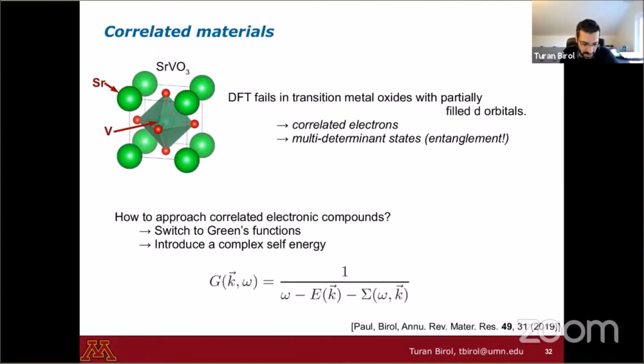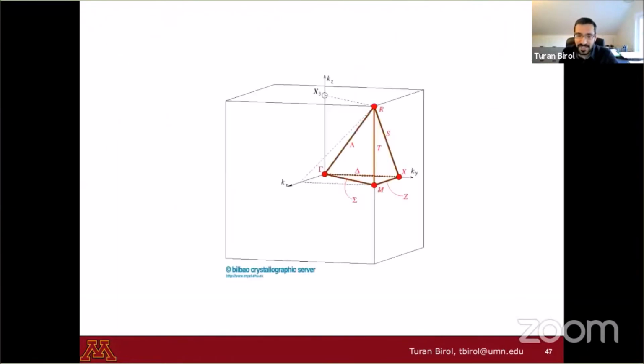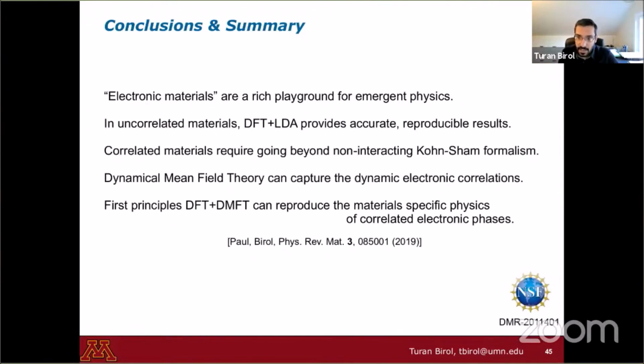That's a great question. So we spent more than a year, and that's actually the main point of this reference I cite in the end, trying to do exactly that. It turns out that in strontium vanadate, due to the simplicity of the cubic crystal structure, strain does nothing. So strain, pressure, etc., doesn't change the plasma frequency, and transparency as a result, at all. Like, just negligible changes happen. But we are still looking for other materials, perhaps layered materials or materials which have more complicated crystal structures, which would be more sensitive to strain, to actually tune the optical properties using strain and other external knobs that we can use in the laboratory.